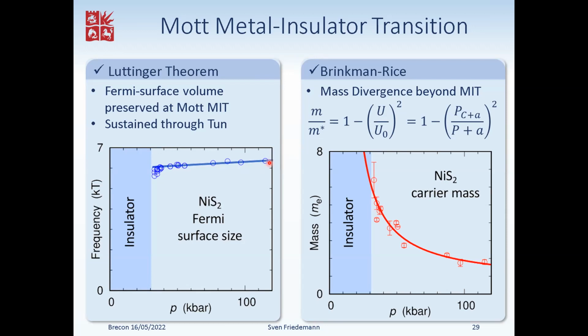At the same time, we can of course use the quantum oscillations to measure the effective mass, and we observe an increase of about a factor of 7 between the highest pressures where we've looked at this down to the lowest pressures close to the insulator transition. We can fit this. You can already see that the line appears to diverge not at the metal-insulator transition, but into the insulating state. It's not completely surprising because the metal-insulator transition is first order, so there is a coexistence region where the true divergence is probably somewhere in that region. But you're saying that despite being first order, it still resembles to quite a significant degree this divergence. And that's also in agreement with single-site DMFT calculations, which predicted the transition to be first order and nevertheless to have a divergence in the effective mass.